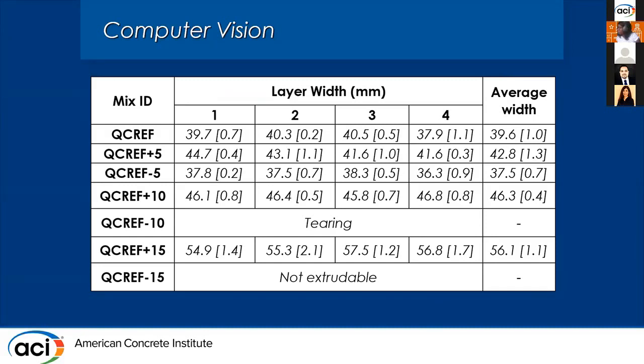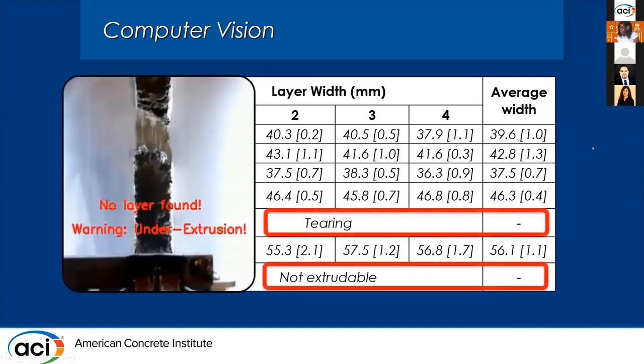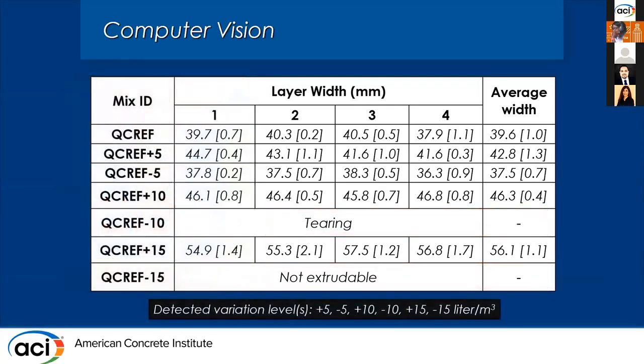And also in 2 cases, because of the low amount of water, we couldn't extrude a continuous layer. So I could see the tearing or even zero deposition for those mixtures. And in those cases, the system was able to detect that as under extrusion. It couldn't differentiate between tearing or zero deposition, but it would report both of them as under extrusion. So it was detected for both cases. And we can say that for all of the 6 variation levels that I designed, the technique based on computer vision was able to detect those variation levels.